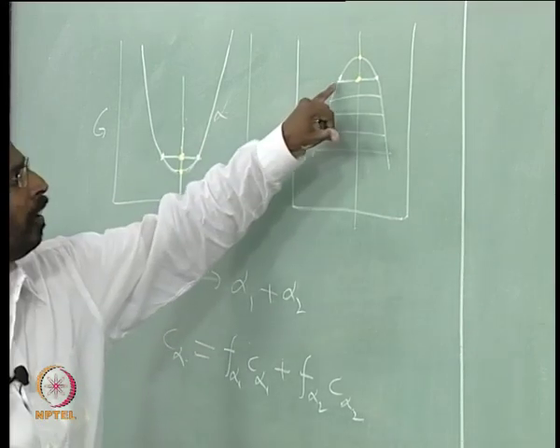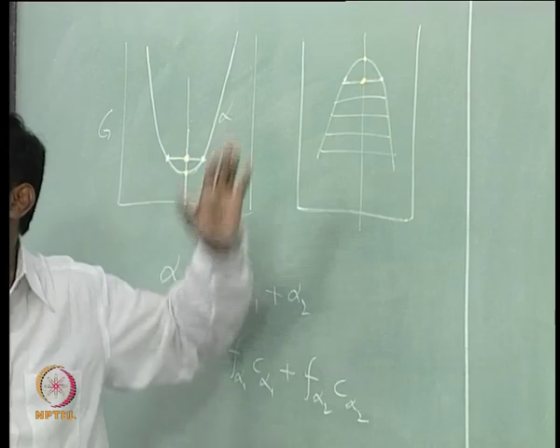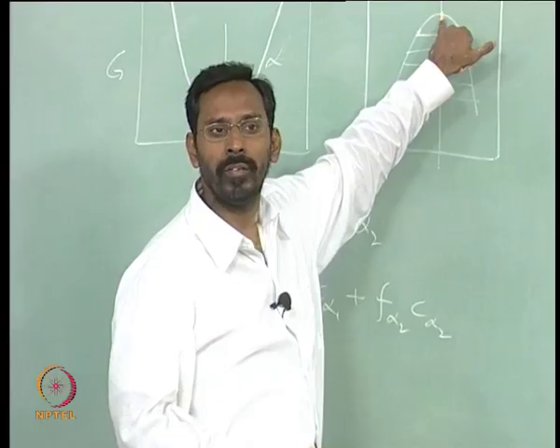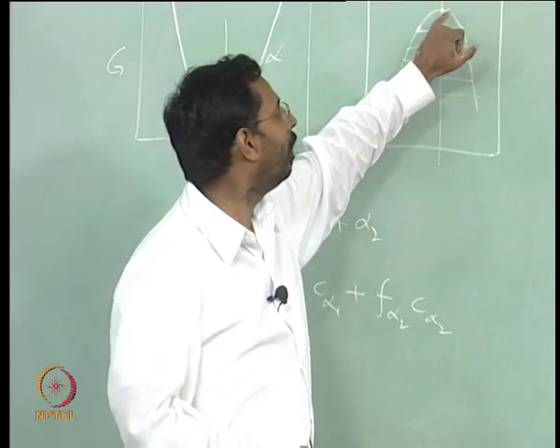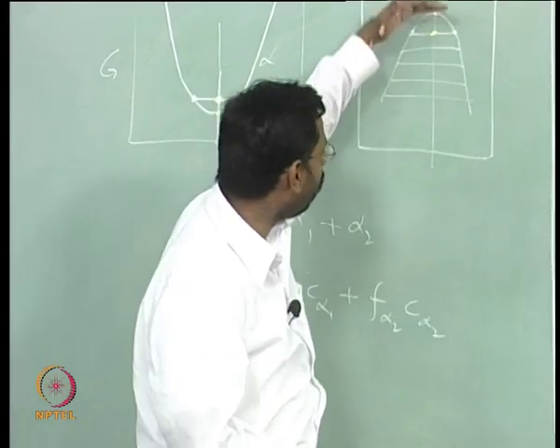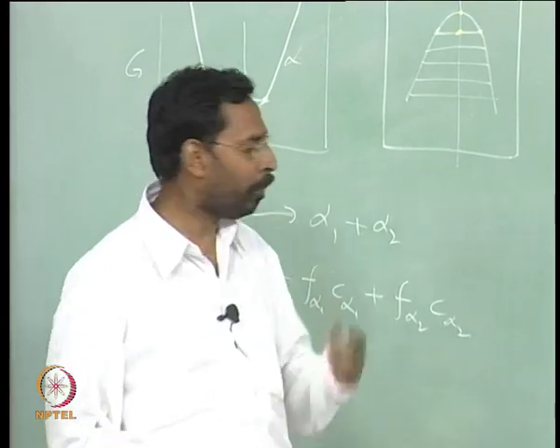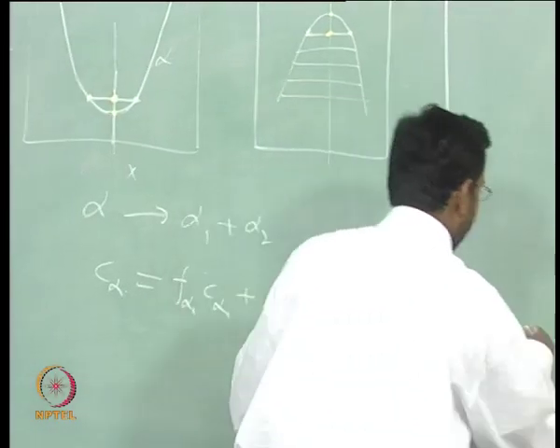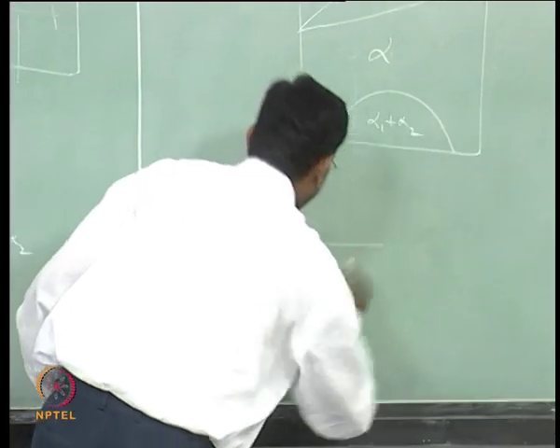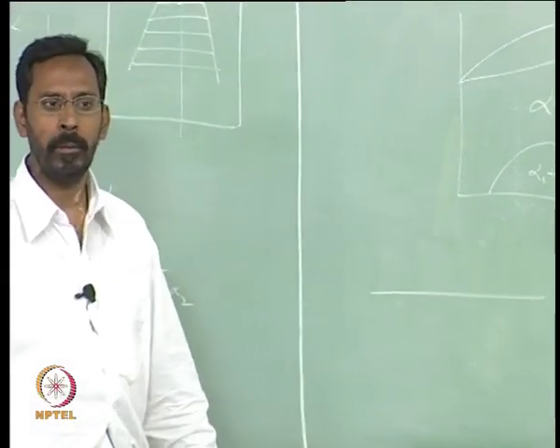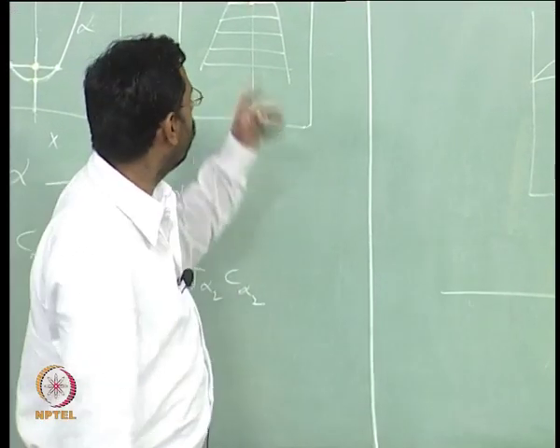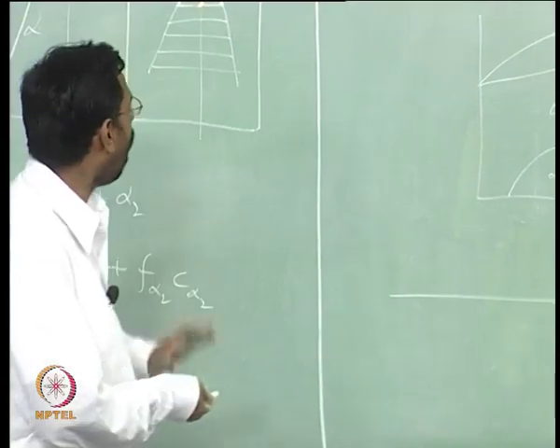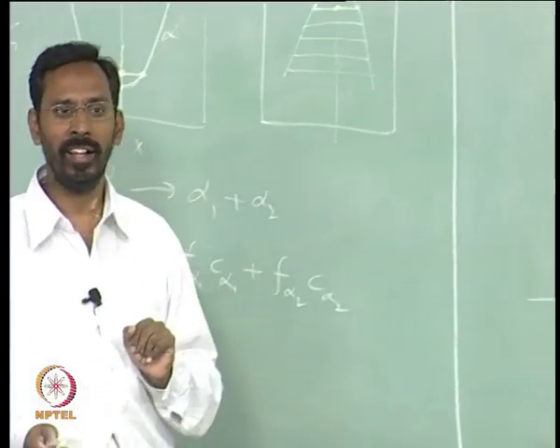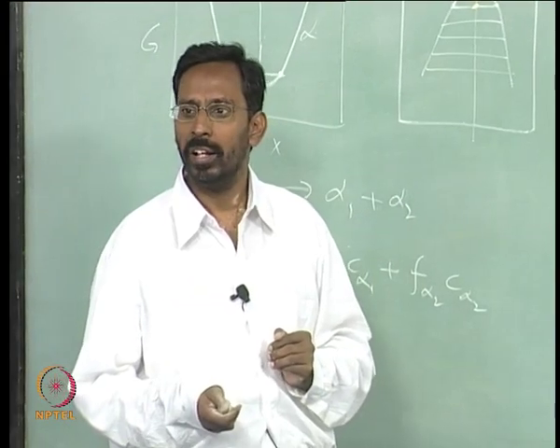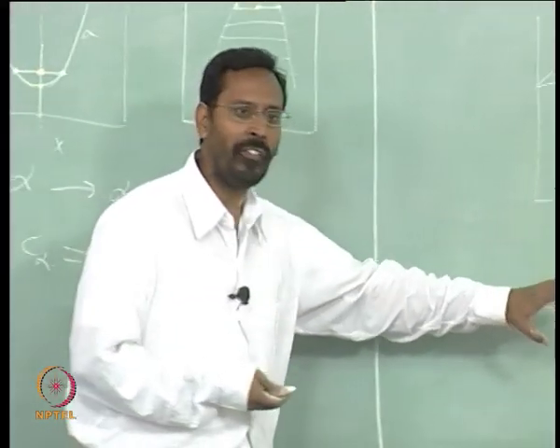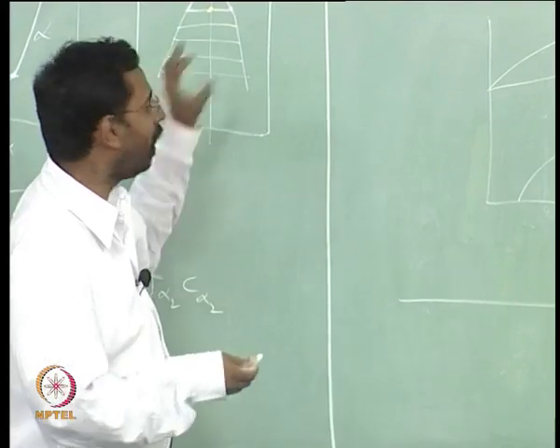That means the alpha 1 and alpha 2 compositions will keep on deviating more and more from the alpha, and this causes a further decrease in the free energy. That means if I start with an alpha having a uniform composition, and this alpha has a free energy curve something like this at a certain temperature, then suddenly this alpha is not stable, because its free energy curve is like that.